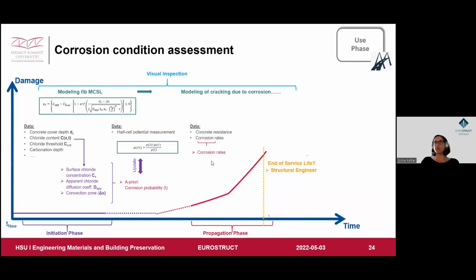And certainly we know that next we see cracking, and that's the reason why visual inspection is always of importance for updating. If we are already in the cracking phase, we should do the visual inspection, and also have the corrosion rate and the concrete resistance. These are both methods which you can do as testing and as monitoring.